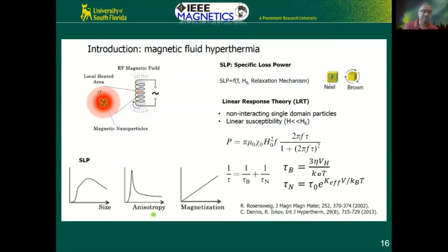There is also a critical size dependence for improving the SAR. It is also called SLP. SLP is specific loss power. It's the same quantity. It's the heating efficiency. You can see there's a size dependence, there's an optimum size. Now, it turns out that the best size for this kind of cancer therapy is somewhere between 20 to 35 nanometers. Not smaller and not bigger, if you look at this curve.